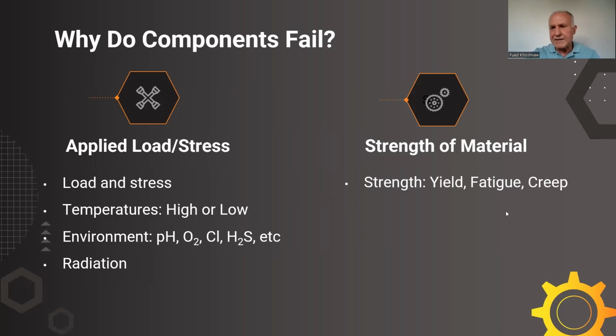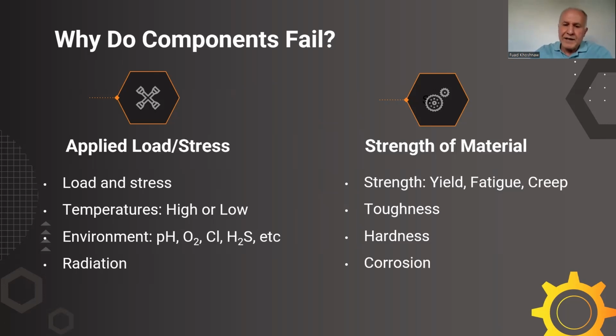And when we say strength, it can be yield strength, fatigue strength, creep strength, etc. All these mechanical strengths. And also toughness. Toughness is a measurement for impact or for crack propagation in fatigue. Hardness: when the material is soft and is in contact with another material, then there is not enough strength. And then corrosion also. Corrosion also has a measurement, which material has high corrosion resistance. So failure can be avoided when this side, the left side, is smaller than the right side.